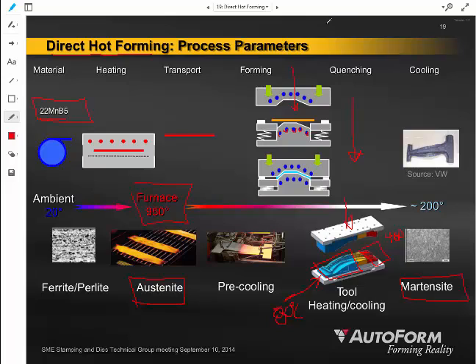So this is something that people might use the term tailor tempered. So tailored, like the guy who fixes your pants or your shirts, tailored tempering allows us to very specifically control the material parameters, the material properties of the finished product by controlling the temperature at which this material quenches. So if I quench just the top part of this B pillar at 80 degrees C and I held the lower part of the die at 400 degrees Celsius, what will happen is that the lower part of the die would